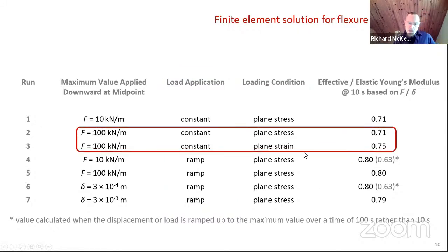I've also looked at two different runs with a constant load, one run for plane stress and the other for plane strain. And I've plotted the effective modulus over the elastic or Young's modulus after 10 seconds. You can see that the plane strain value is greater. So effectively, by restraining the beam, the viscoelastic behavior gives a slightly stiffer result. That's kind of interesting. And in most situations, what one would get is somewhere between plane stress and plane strain.